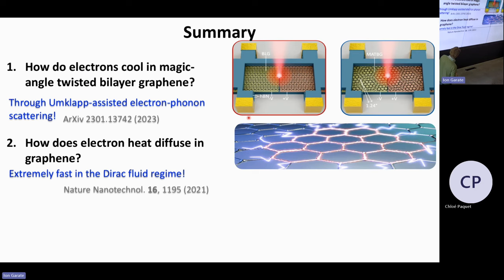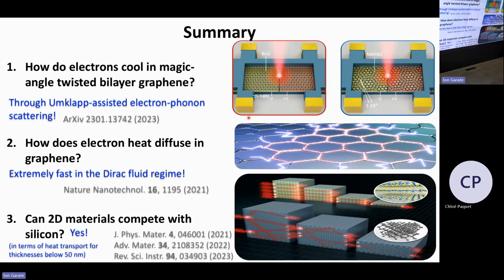Okay, that brings me to the summary of my talk. So I showed you this twisted bilayer graphene with very fast cooling at low temperatures through this Umklapp-assisted electron-phonon coupling. I saw this very fast diffusion of electronic heat in the Dirac fluid regime. And we believe that 2D materials can actually start competing with silicon, at least for very thin films and considering their thermal transport properties. So that doesn't mean that they're for sure going to make it and make everything great. But at least the thermal transport properties are not a bottleneck to start considering them for applications in transistors and others. So with that, I'd like to thank you for your attention.